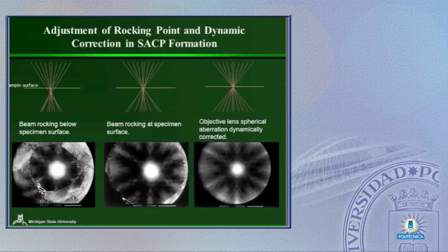But first of all, what happens if we don't rock this beam on the surface of the sample? Let's imagine now it's rocking down here, and that's very common in a lot of microscopes. Well, certainly then as you rock the beam, it's going to sweep across the sample. And so if you cross things like grain boundaries or into different orientations, we're going to get channeling information from those different orientations. And so this means that the spatial resolution of the technique is really quite limited. So if we can adjust this rocking point and put it right on the sample, we can certainly get information from a smaller area, which becomes more useful for us.